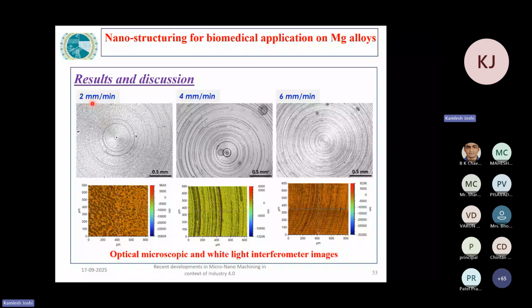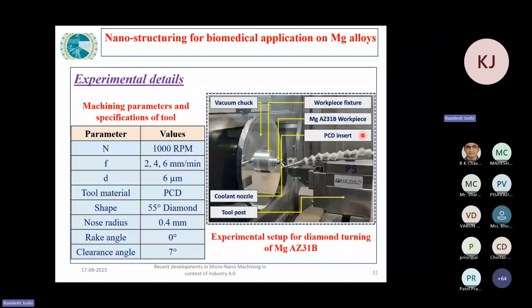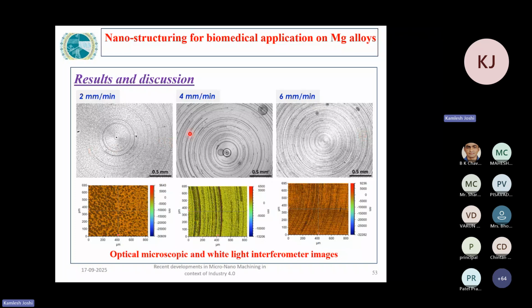You can see the surface machined at 2 mm per minute, 4 mm per minute, 6 mm per minute. As we increase the feed rate, you can see the rubbing marks or cutting marks are more visible on the surface.